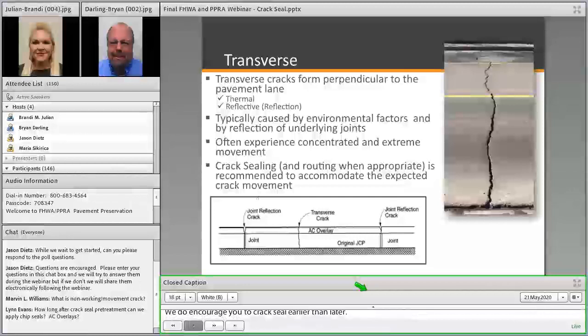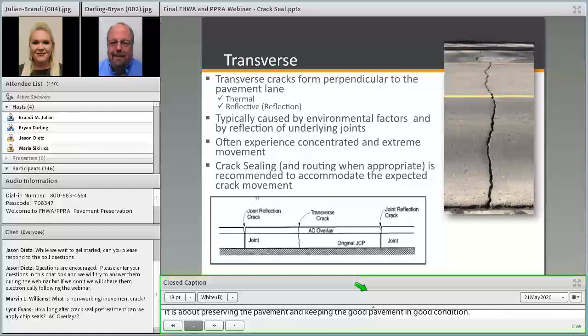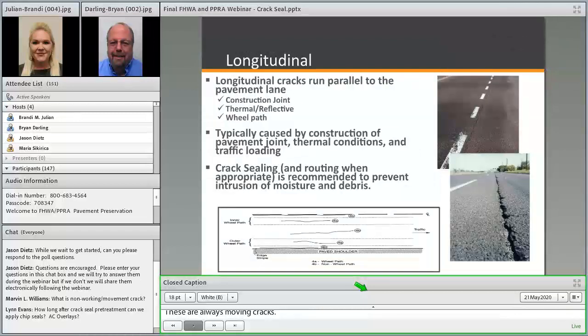So looking at the types of cracks, this is a transverse crack that's running in this photo here. You can see it runs perpendicular to the driving lane. We always anticipate that these are high-moving cracks. They're formed often in one of two ways. Thermal, which we've talked about a lot here already. Or the other way it's formed is if it's an AC overlay over an existing concrete roadway, anywhere there is a joint in that underlying concrete pavement, we're going to anticipate that movement from that underlying joint is going to reflect up through that asphalt overlay, and you're going to get a crack there. These are always moving cracks, and we definitely encourage routing and sealing in examples such as this, and selecting a really good sealant that's going to be able to accommodate that movement that you're going to achieve between seasons.